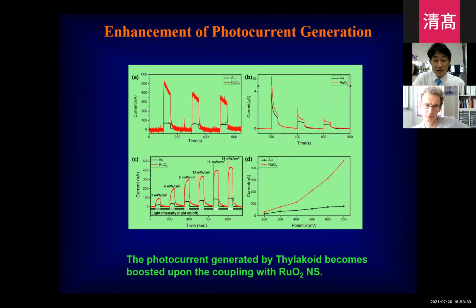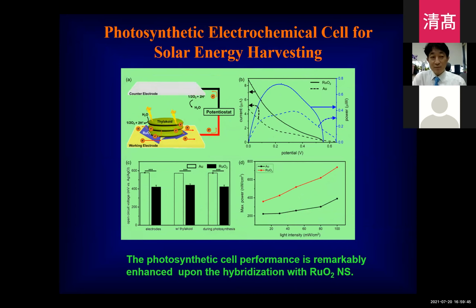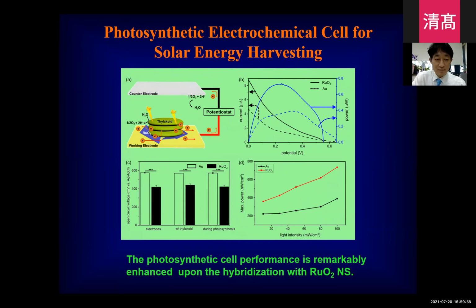So by incorporating ruthenium oxide nanosheet as an interlayer, we observed a drastic enhancement of photocurrent, as you can see here. We fabricated a photosynthetic electrochemical cell. As you can see here, compared with the ruthenium oxide nanosheet-free cell, the ruthenium oxide based cell shows much better performance as a photosynthetic photocurrent generation.